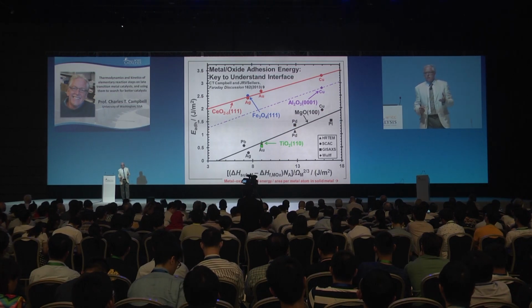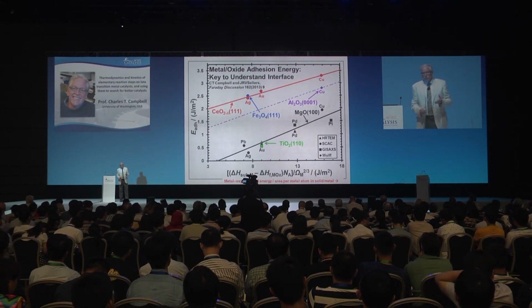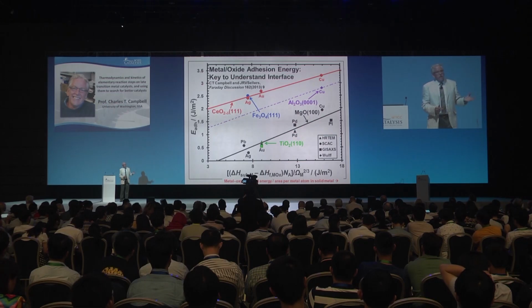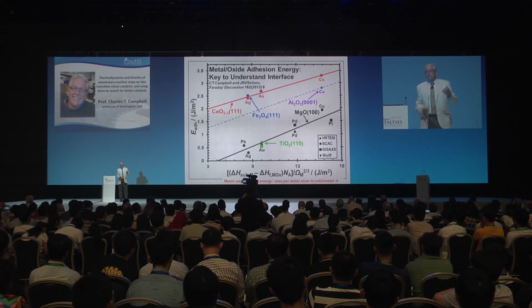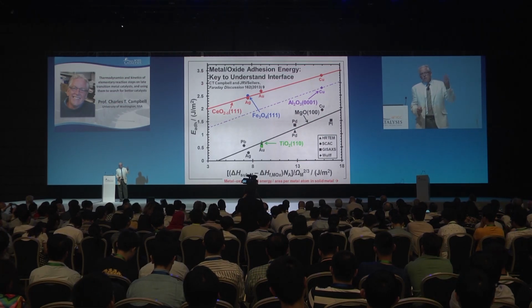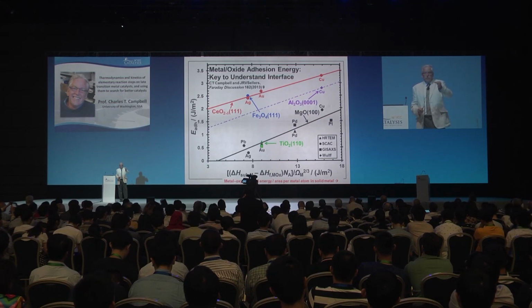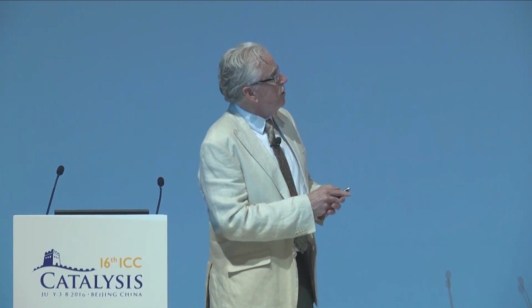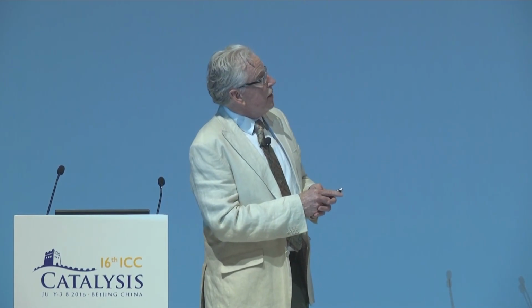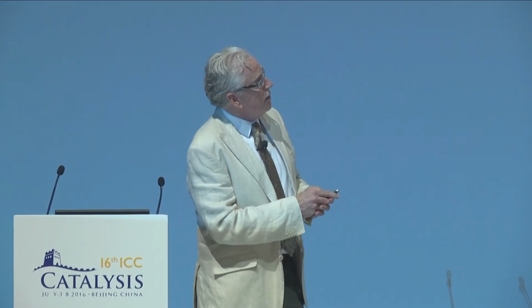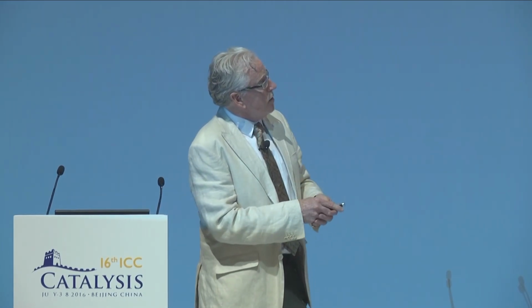Strength makes sense because when folks do density functional theory of metals like these on oxides like these, they find that the metal atoms prefer to sit on top of the oxygens. That is, they're bonded primarily to the oxygen atom. So the strength of metal-oxygen bonding should correlate with the adhesion energy, as we see here. It does. These are new results for slightly reduced ceria. And these are following a similar slope, but much increased.